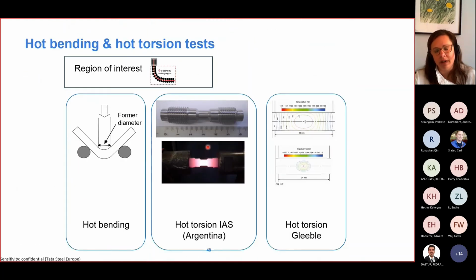But there are also some other tests that are very important for the secondary cooling region. It's not such a high temperature, not during solidification, but they are extremely important. We have hot bending tests, torsion tests, and there could even be torsion tests on the Gleeble itself. Together with Warwick, we are now exploring the hot bending test.